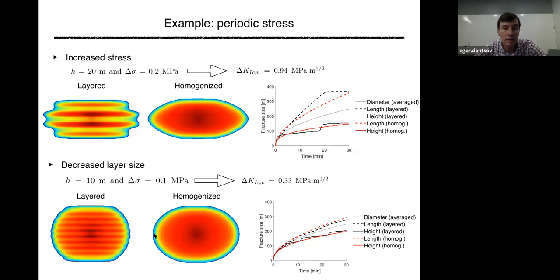One remark here is that, if you remember, for the fracture toughness and modulus, the results are not length scale dependent, right? It doesn't matter how thin your layers are, as long as linear elastic fracture mechanics works. But with regard to stress, this is length scale dependent. If you have the same magnitude of stress oscillation but larger layers, then you have more effective fracture toughness. If you have very thin layers with the same amplitude, you're going to have less fracture toughness, as shown here. This is a very, very important observation.